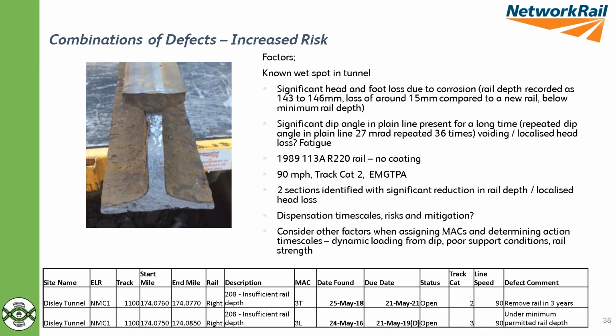Some of the things we've been looking at, we still suffer problems in wet tunnels or local areas of corrosion, level crossings. This is an example, it's a broken rail, but a huge amount lost on the foot, off the head of the rail at that point. So a loss of rail depth at this point, a very worn, flattened head profile. But again, a defect there that resulted in a broken rail.